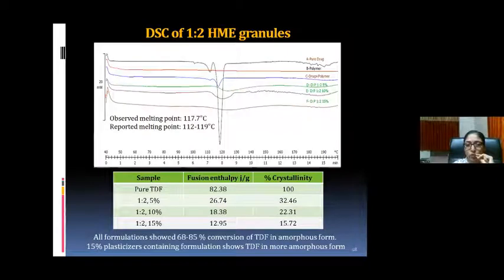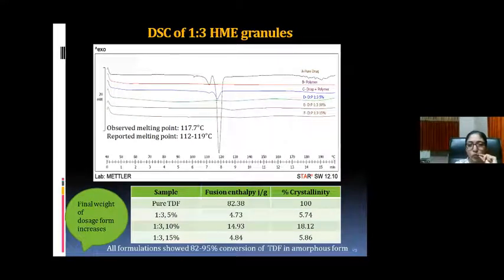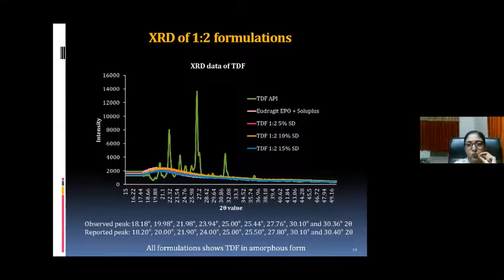So we moved to the 1:2 ratio, where again the percentage crystallinity was calculated, and all the formulations showed nearly 68 to 85% conversion of the TDF into amorphous form. The formulations containing 15% plasticizer show the TDF in a more amorphous form. If we move to the next concentration, all the percentage crystallinity results show 82 to 95% conversion of TDF into amorphous form at 15%. But the final weight of the dosage form is going to increase. Even in the XRD studies of the 1:2 ratio, all of the formulations show the TDF in amorphous form.